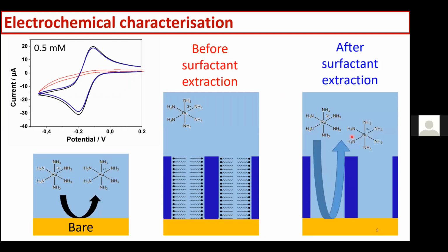calcination or by acidic ethanol solution, we can remove the surfactant, and then you get the CV almost back to normal. So it means that the electrode surface is available again for the reaction, but the film is still there. So we're only removing the surfactant there.